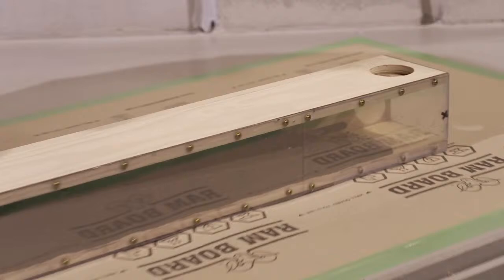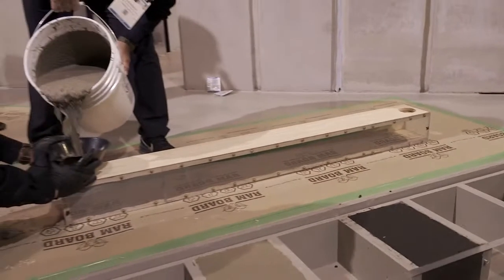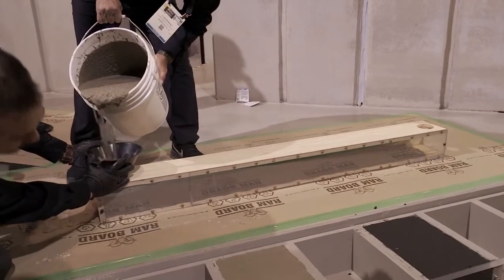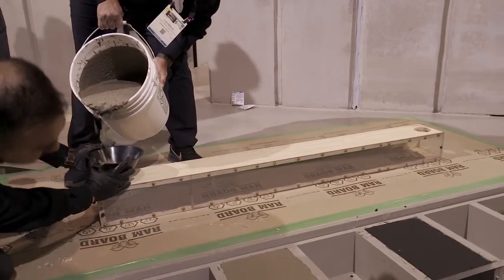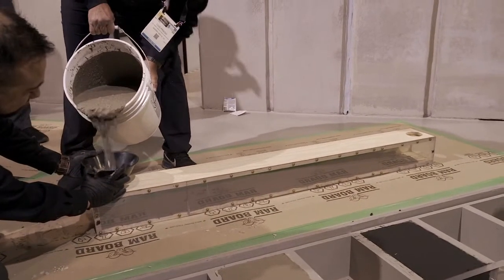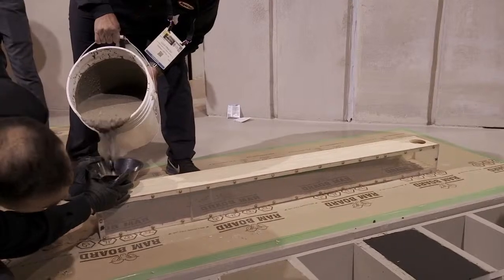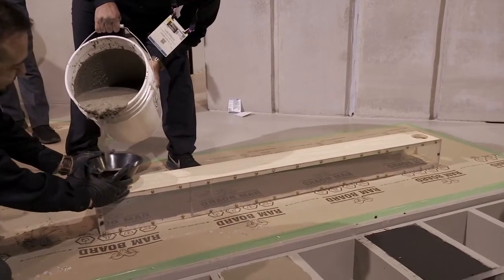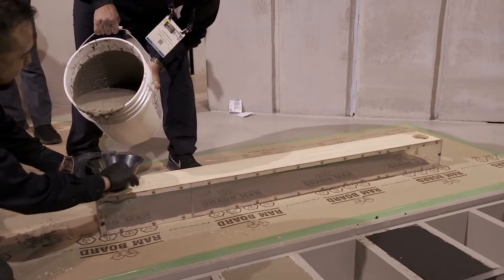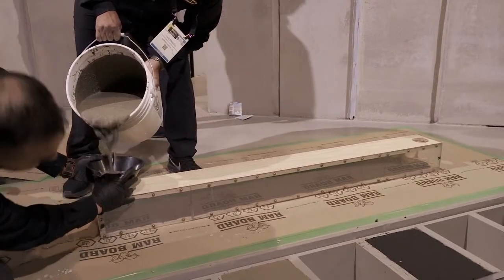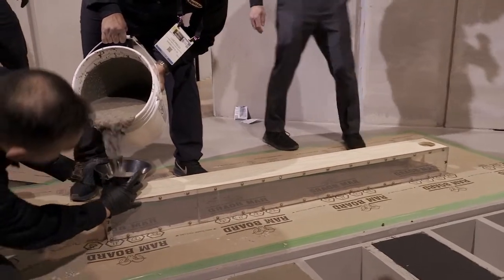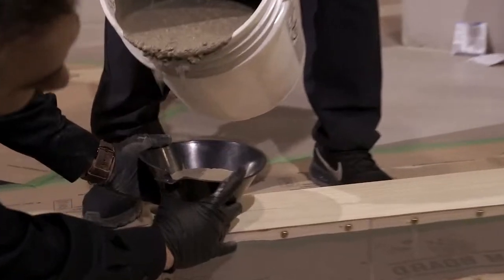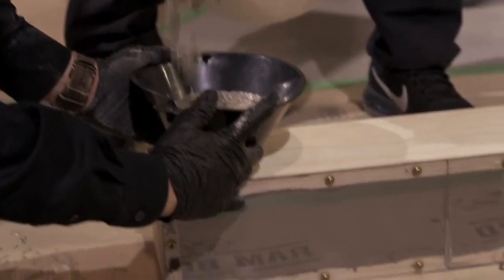So this product's designed for about 30 minutes of flow life, but it'll gain 2,500 psi in 4 hours and 6,500 psi in 28 days. I can see it's making it all the way over to the other side of the box right now.